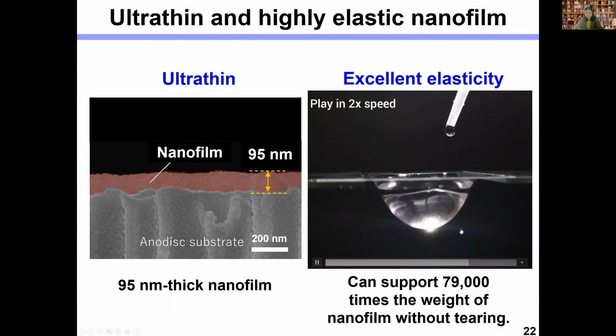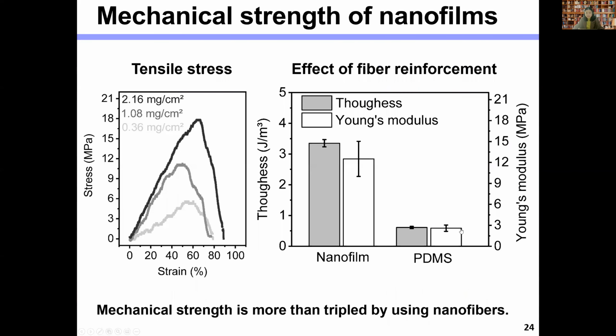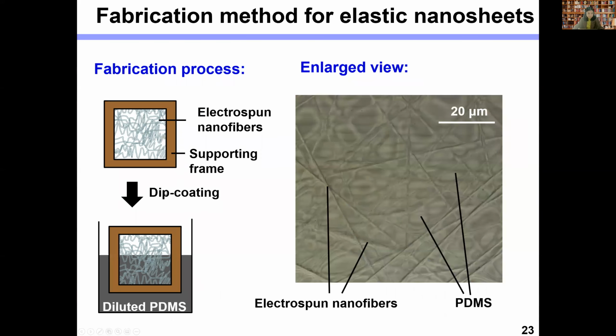So why does this film exhibit such high robustness? From the fabrication process, we can see the film is reinforced by nanofibers. In the beginning, we first electrospun a nanofiber mat with a PI frame to support, and then we dip coat the mat into diluted silicone rubber solution. And after drying and curing, we have the nanofiber reinforced PDMS nanofilm.